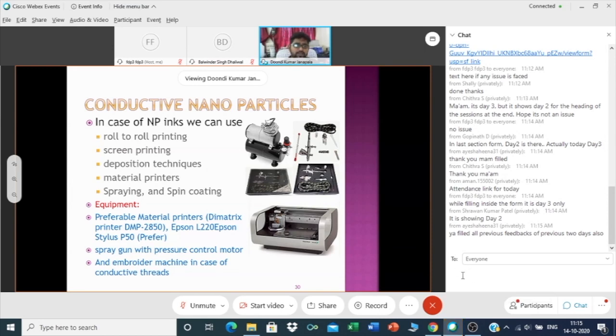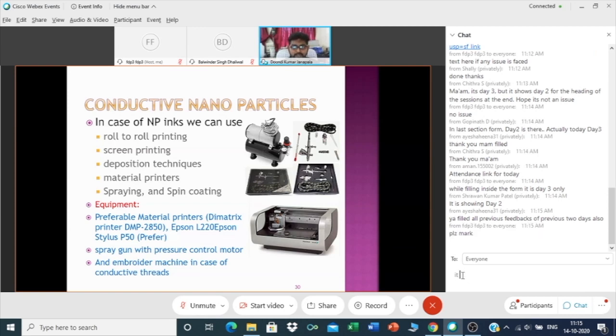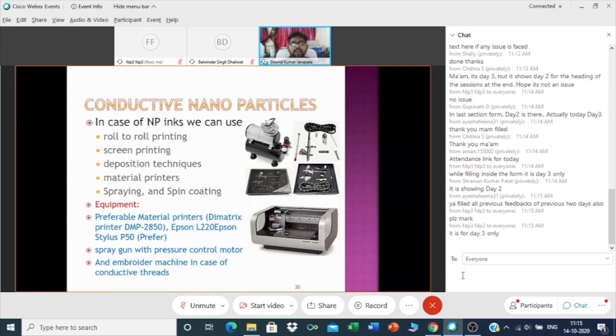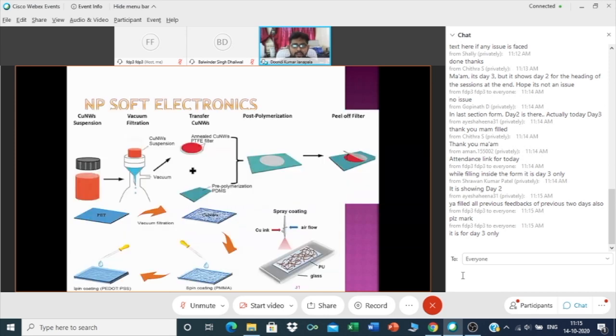And another advantage of taking a preheated polymer is, that heat will enable the polymer surface to absorb those nanoparticles to its surface properly and hold them. Then you will have proper adhesion between the polymer substrate and your nanoparticles. That is one good thing if you are taking a preheated polymer for spraying.